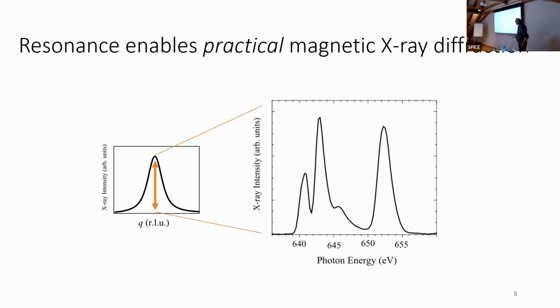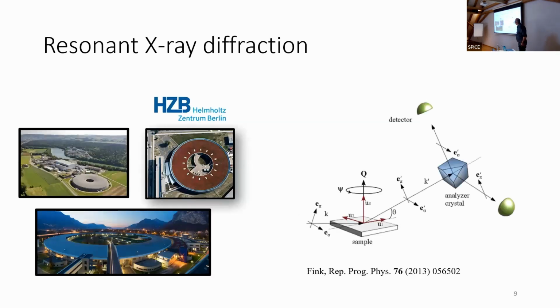Again, this is just to emphasize what we want to do. This is one of the slides that suffered greatly from the absence of Wi-Fi in the hotel. And this is another one of them. So this is the technique that we're going to be using. Essentially, we're going to scatter light off of a sample. Light comes in, light goes out. It goes into a detector, which can resolve its polarization. We can control the incoming polarization. And all of the experiments I'm going to be showing today were done statically at SLS at ESRF and dynamically and statically at BESSY. All the time resolved work was done at Femtospex, which is the slicing source for soft X-rays in BESSY, which is a lovely, lovely source. We love it.